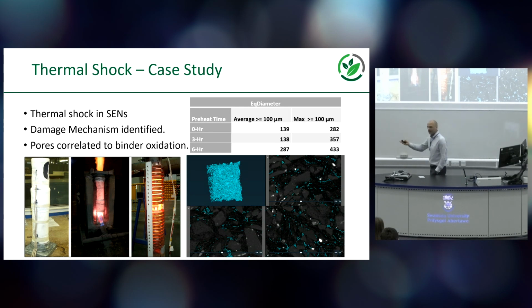So before you put them in, this is for casting, by the way, so the material flows through here into the tundish. And you obviously don't want to put them in cold because they just break straight away, so they need to be preheated. But when you preheat them, you then start to initiate that oxidation process, which reduces how robust they can be and can lead to premature failure if you do it wrong, which was happening. And so we worked between the refractory manufacturer and Tata to try and look at how we would do this, but sneaked in some cool characterization along the way.